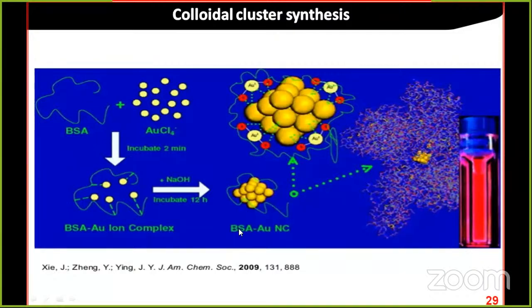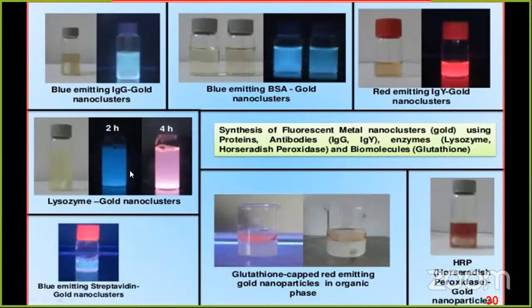The drawback of this one is that BSA is very expensive. It is a protein and needs dark room conditions, 12 hours heating, and a temperature of 40 degrees. So if you fail to meet these conditions, you cannot prepare it. This is the main drawback of this nanocluster. There are many particles people have reported. This blue one is BSA, this is antibody, another one antibody with red fluorescence, and this one is pink fluorescence, lysozyme. Many kinds of fluorescence people have developed. But among the different ones, red fluorescence is highly valuable.